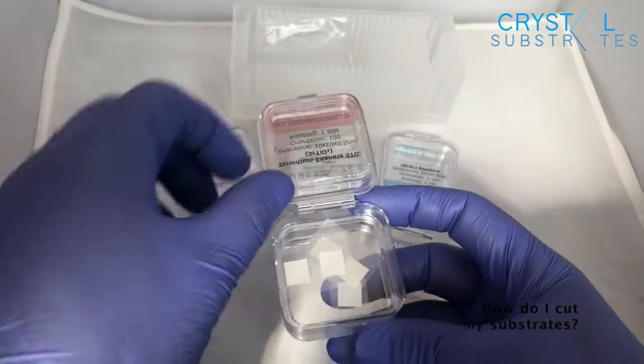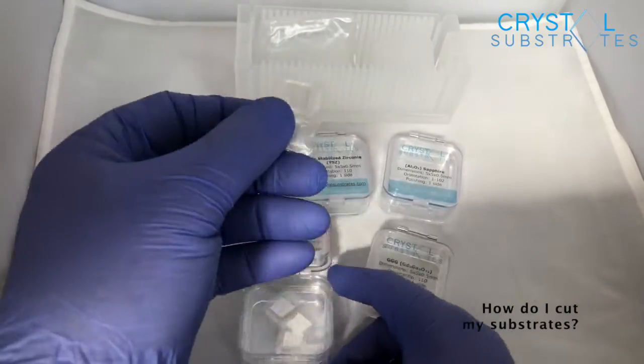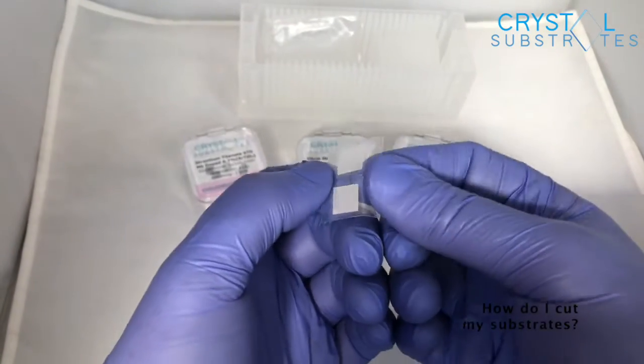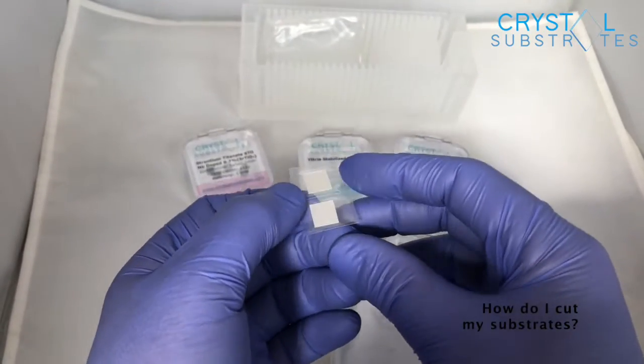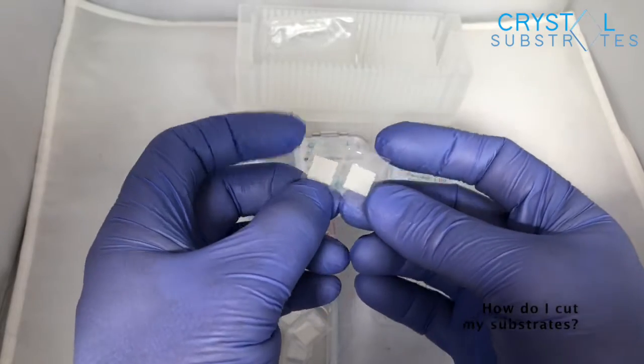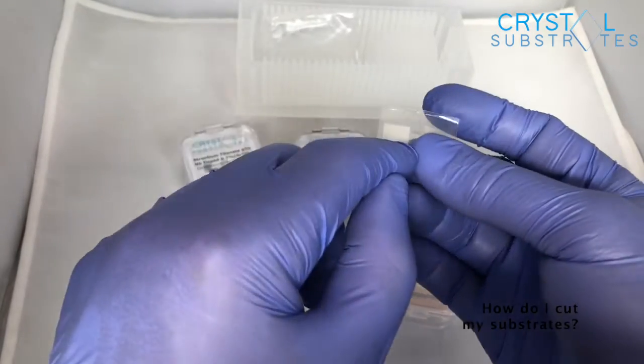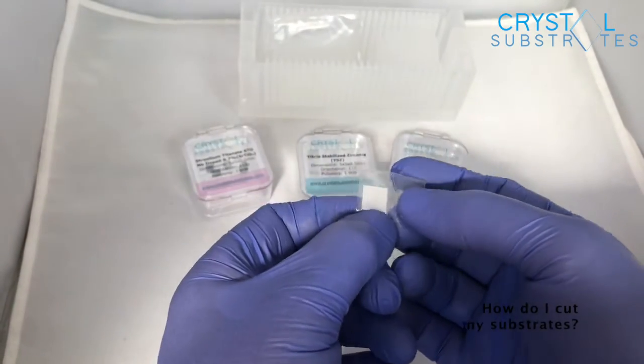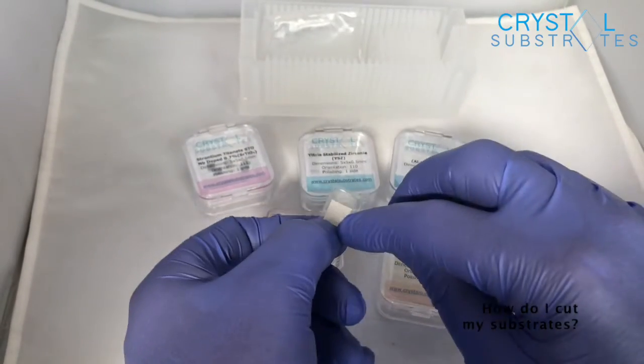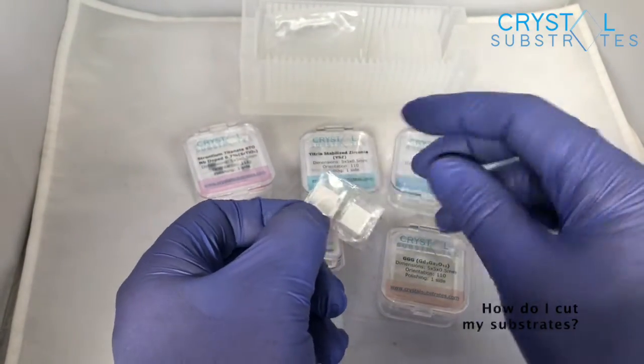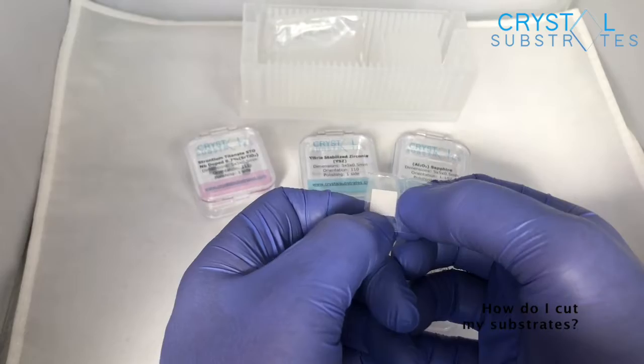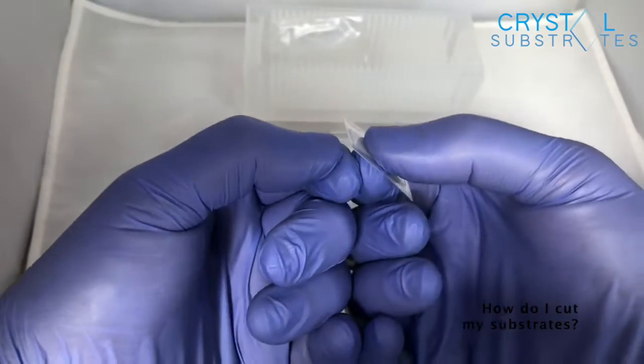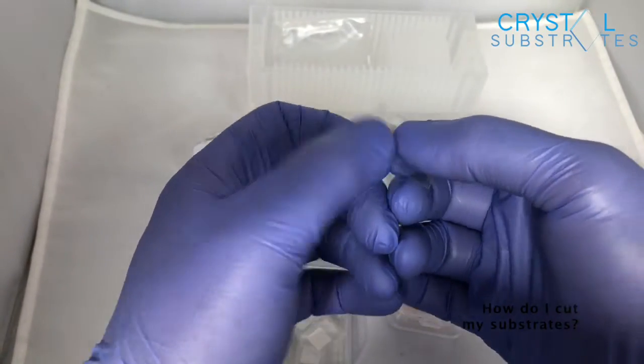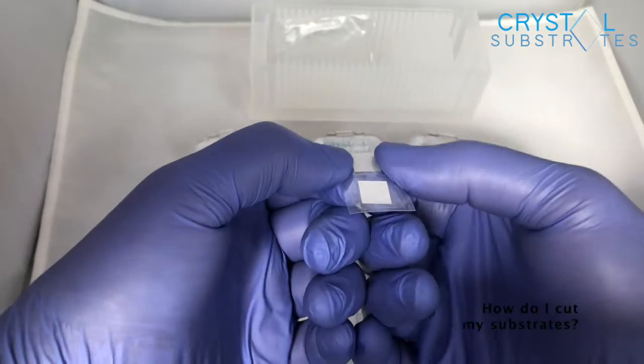So what you do is you take this out of the packaging, and you'd find the shiny side. In this case, this is one side polished. Then you turn it over so you're on the non-polished side. You then take a scribe and a rule, a diamond scribe, and you'd run the scribe along the back. You don't need to push too hard, make a straight line, and then you just snap it with your hands along that line, and then you can do the same in the other direction.